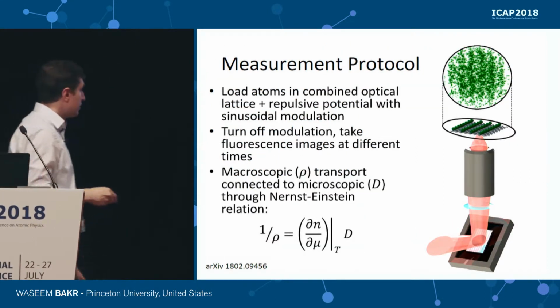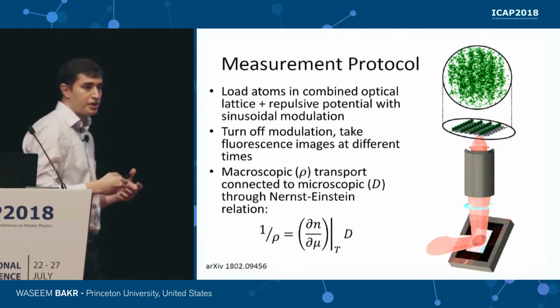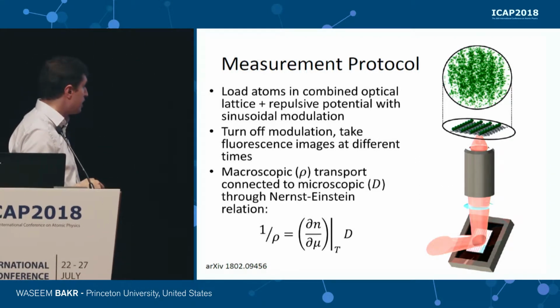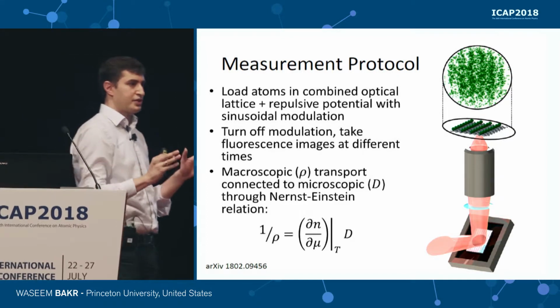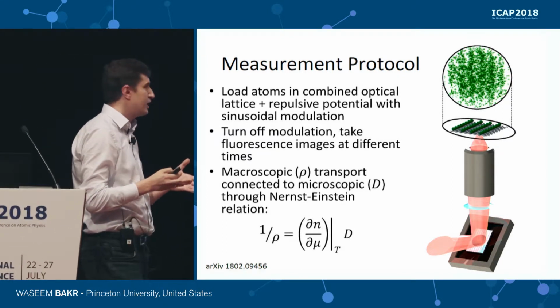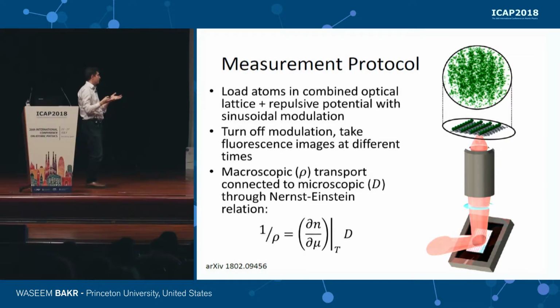Okay, so let me tell you now about the transport experiment we've done. We're interested in measuring bulk resistivity in the system, and we want to do a really clean experiment at a fixed doping. In cold atom experiments, usually the density is varying due to the presence of a harmonic confinement because of the Gaussian lattice laser beams. But in our experiment, we have actually flattened the trap near the center using a spatial light modulator. We send light that forms an extra repulsive potential that produces a flat trap in some region of the cloud. And so we just have a Hubbard system with a uniform density.